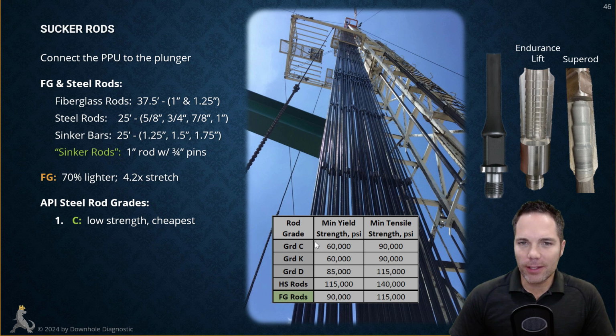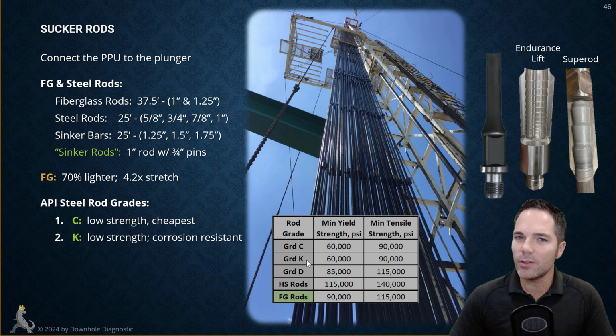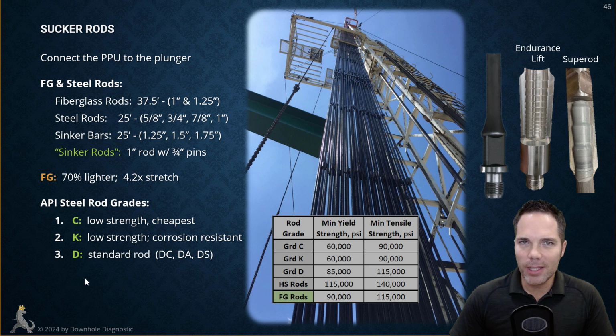So if we go to the table here, this is also in my rod pumping brochure, you can see a grade C rod. The yield strength is 60,000 pounds per square inch, and the tensile strength is 90,000. Well, a grade K is the exact same right here for these properties. So grade K, it's also a lower strength rod, but it's more corrosion resistant. It has more alloying elements in it to better resist corrosion, but it has the same tensile properties as C does. So these rods right here work well if you have a shallower well. They're usually good up to about 4,000 to 5,000 feet, depending on the diameter of your plunger. But once you get beyond that, these rods are going to start to be overloaded, and you need to look at a higher strength rod, and that would be grade D.